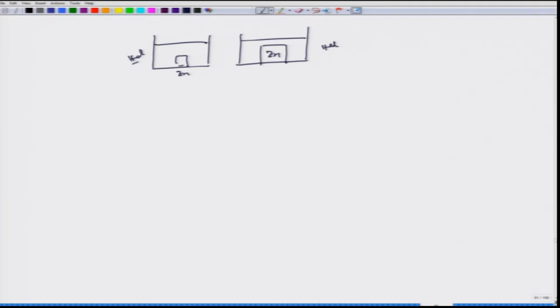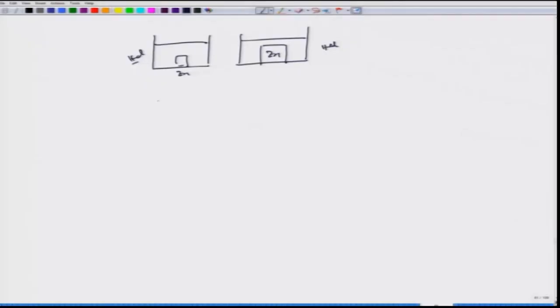But many times, for example, in case of atmospheric corrosion of iron, we do not see that. If we start from zero time and after spending certain days, you take out that particular metal piece without disturbing the surface conditions, that means you are carefully taking the sample without disturbing the surface and weighing the particular small item or the plate that you have exposed to the environment, you might see that there is weight gain rather than weight loss. So in certain cases, we see that there is weight loss and it becomes straightforward.